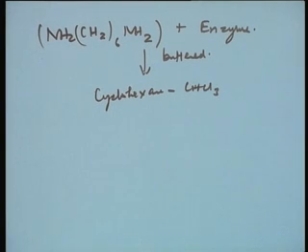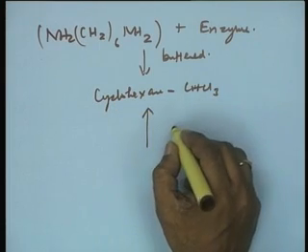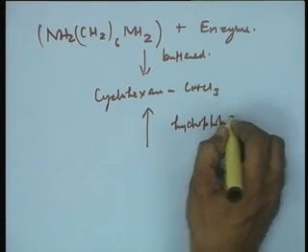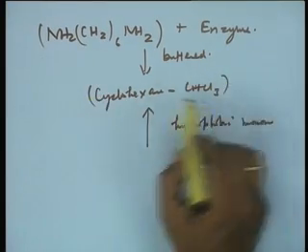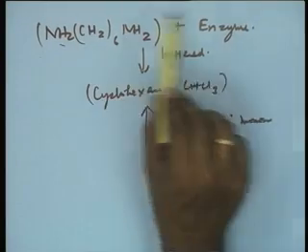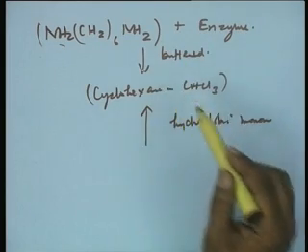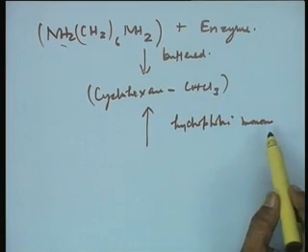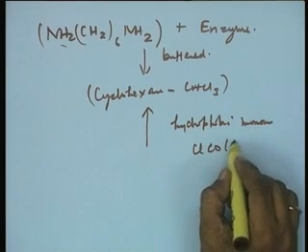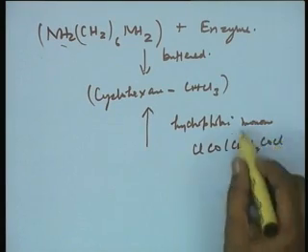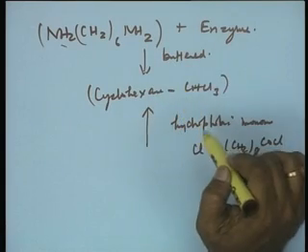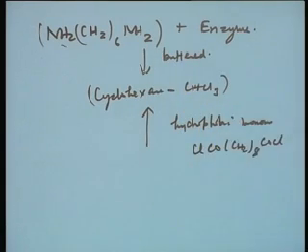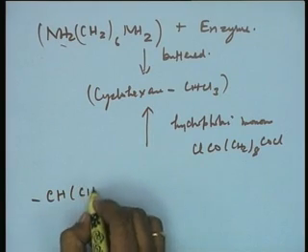Now, this buffered preparation of hexamethylene diamine and enzyme is emulsified in an organic solvent, and the emulsion is added to a cyclohexane and chloroform mixture, to which you add a hydrophobic monomer, in this case sebacyl chloride, dissolved also in the same solvent. At the interface the two monomers get polymerized, and essentially the reaction gives you a polymer that we know as nylon.